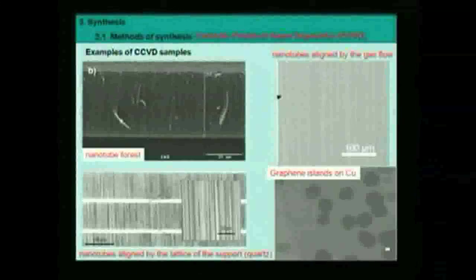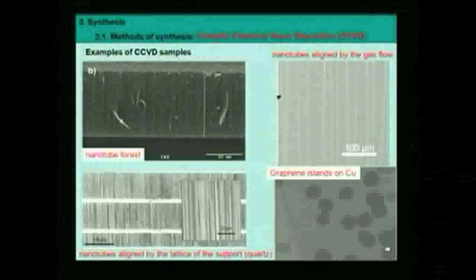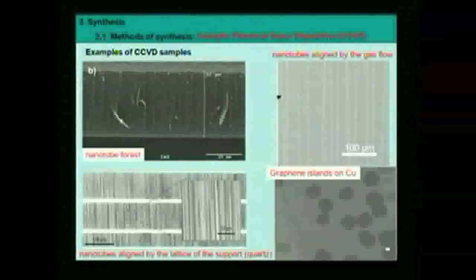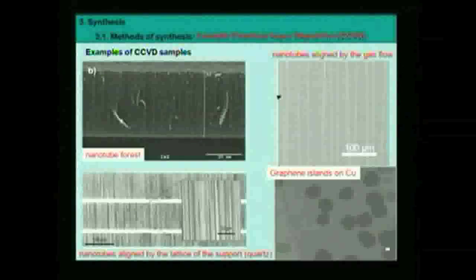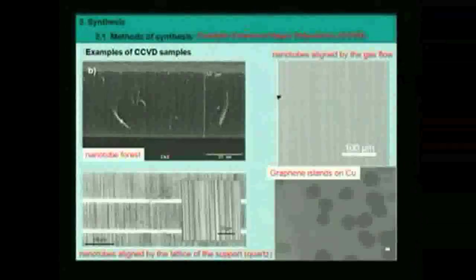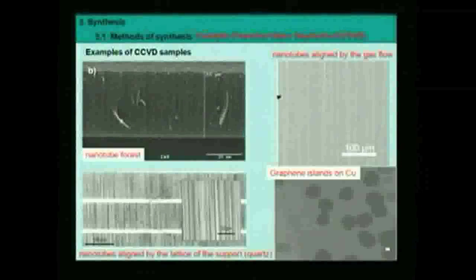So it's like an undulated layer, the substrate, and the tubes go into the bottom part of this undulated layer, because this is where they have the maximum interaction with the substrate. And the interaction is van der Waals type interaction. They maximize their van der Waals interactions in the bottom part of this undulated surface. But not all surfaces have this shape at the atomic scale. So these are very, very thin waves. It's really at the atomic scale.